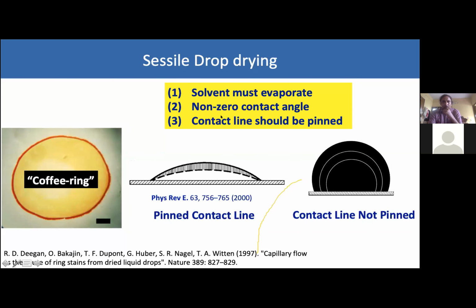The second condition is that the fluid should make a non-zero contact angle with the substrate. That means if you have a very thin film of fluid which completely wets the surface, then coffee rings are not going to form. Therefore, it should form a droplet with a finite contact angle, and the contact line should be pinned. Again, I mentioned this in the previous slides, that there are some nanoscale heterogeneities on the surface which are inherent to the glass substrate or any substrate that one deals with. The pinning is ensured, and of course, when you don't have any pinning, the coffee ring is not expected to form.